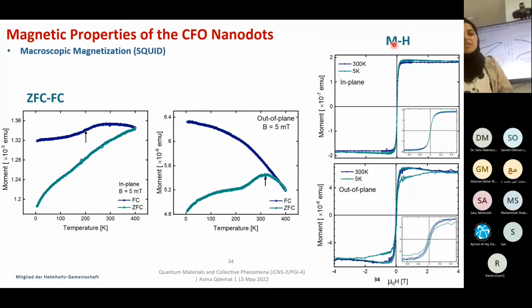Also, we performed magnetization as a function of the field. Here I forgot to mention that in plane it shows a magnetic moment higher than out of plane, which is an indication that the particle is more energetically favorable to align along the field. For magnetization versus field, we performed two temperatures, room temperature and 5 Kelvin. For the in plane case, in both cases, room temperature and 5 Kelvin, it shows a superparamagnetic behavior, no hysteresis appears, and it fits with the Langevin function.